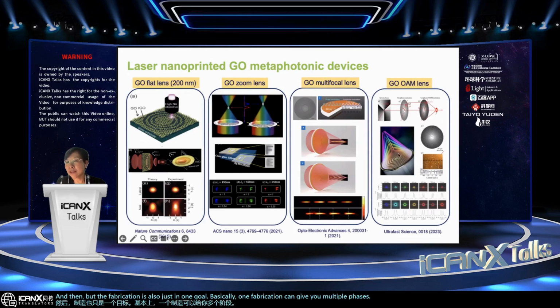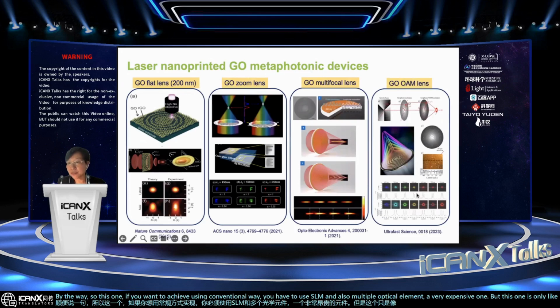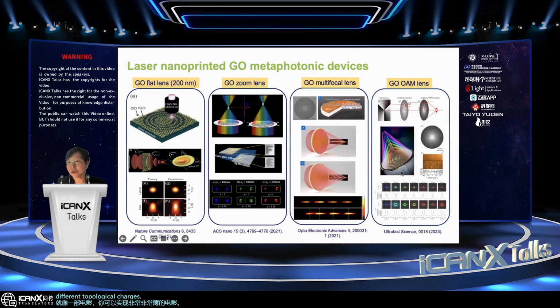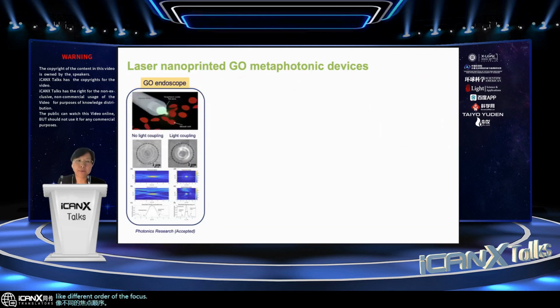And this way, you can achieve this kind of OAM beam, which is very useful for quantum optics and also for laser trapping. By the way, if you want to achieve this using the conventional way, you have to use an SLM and multiple optical elements, very expensive. But this one is only one film, a very, very thin film. You can achieve different topological charges and different orders of the focus. In the meantime, because the graphene oxide lens is so tiny, we can integrate that into the fiber tip.